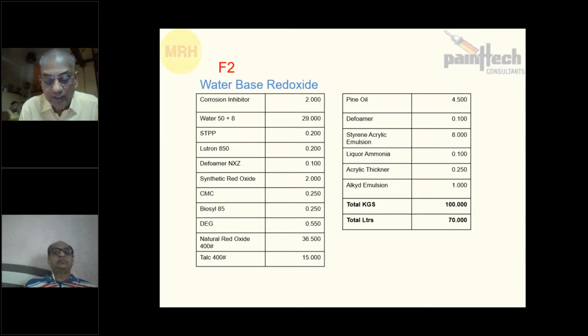First, adhesion. One challenge is substrate wetting. If you take a panel, take water, you cannot spread it on the panel due to surface tension, and you will get a lotus effect. So to apply water-based paint, you require a substrate wetting agent. Then again, you require some adhesion promoter, because on iron a water-based system will not have adhesion. Some silane or something you have to take help of. And film hardness and non-permeability also you have to take care of.